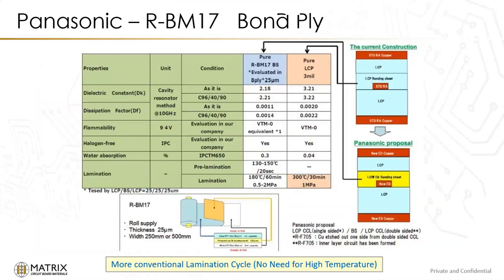So to go with the LCP, there is a bond ply available. It is the RBM17 bond ply, and it has some very, very good properties that go with that, so it allows it to bond the LCP together. And we can look at, of course, the dielectric constant's got to be low, otherwise it takes away from the performance of the LCP. We're also looking at the dissipation factor. If we're looking at the LCP, it actually exceeds that 0.001 as is, 0.0014 dissipation factor.